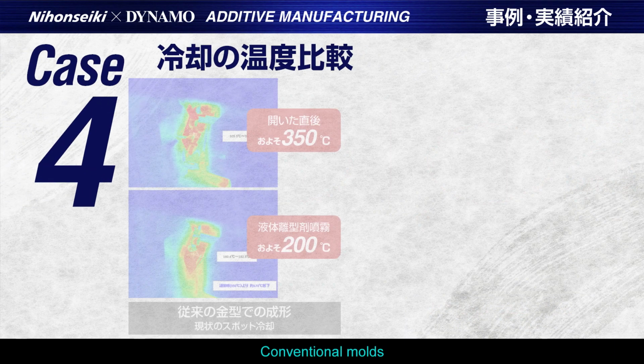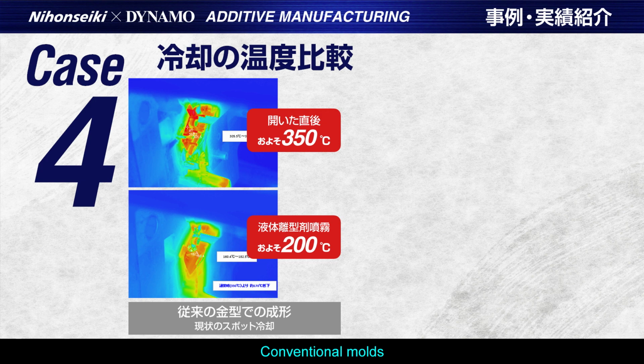Case 4. Temperature comparison. Images of a mold using conventional drilled spot cooling. The upper image shows the temperature after casting, which is about 350 degrees Celsius. The lower image shows the temperature after spraying the mold release agent, which is about 200 degrees Celsius.